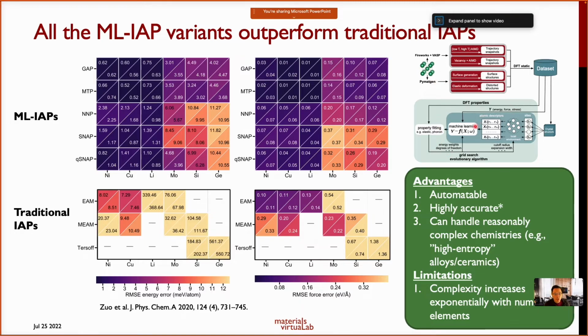Now, that's one of the main advantages of machine learning interatomic potentials, but it's not the key one, right? The key advantage of machine learning interatomic potentials is that they are highly automatable, right? This is a workflow that was developed in my group, where we basically developed an automatable recipe for generating an interatomic potential for any system. This was how we were able to generate so many potentials for so many different systems in a very short amount of time. The second advantage is that, of course, they are highly accurate, as this plot has shown,